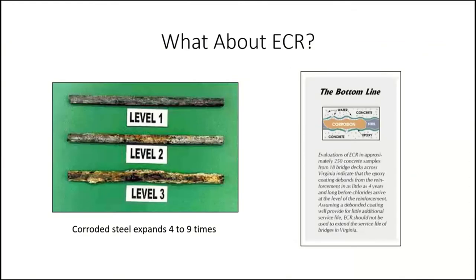I did reference a study that was done in Virginia a number of years ago where they were looking at epoxy coated rebar. They had 250 samples from 18 bridge decks, and within 4 years they started seeing the corrosion of the steel within the epoxy coating. And once you have a little nick in that epoxy coating, you have kind of a concentrated anode. It just takes off inside that coating, and the reinforcing starts to expand, as you can see.